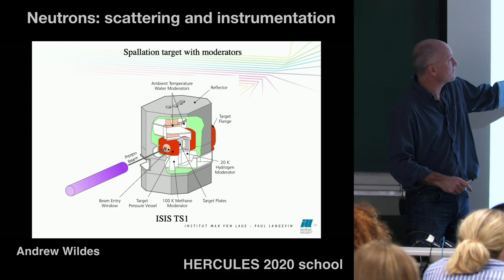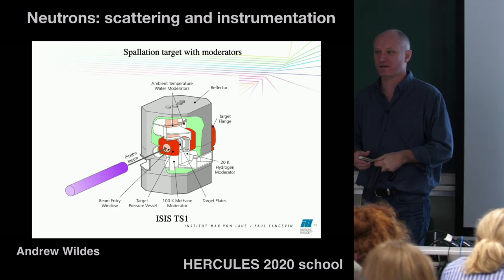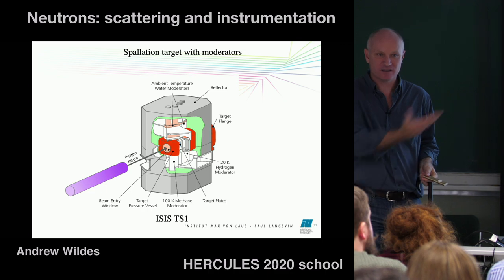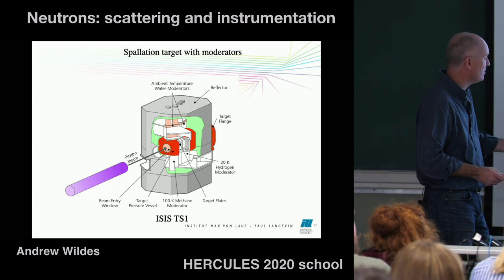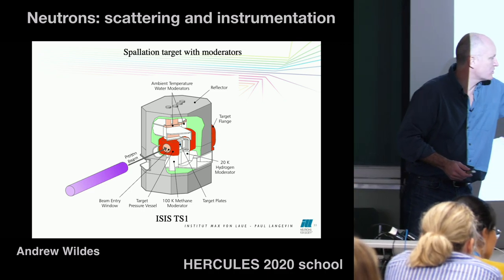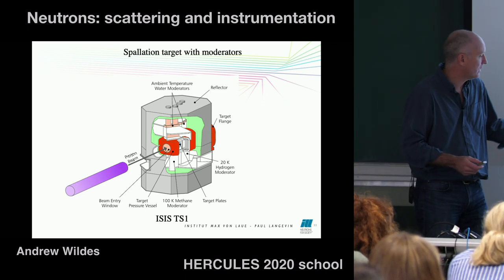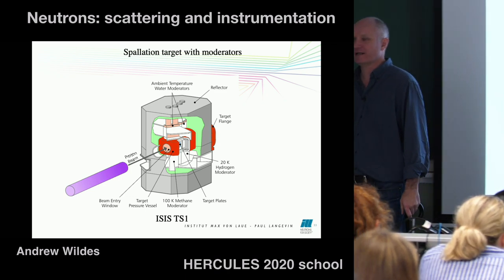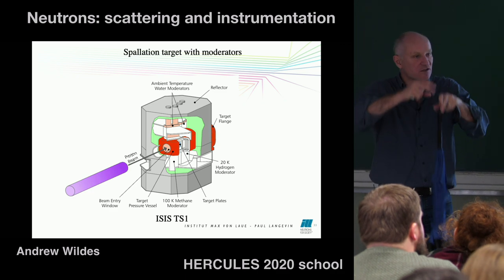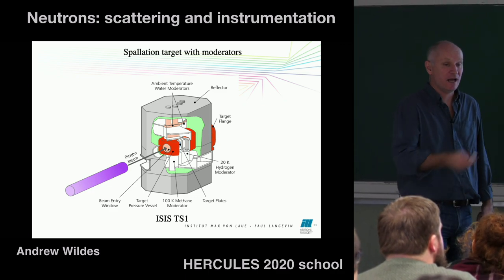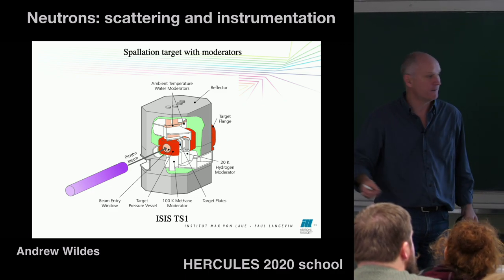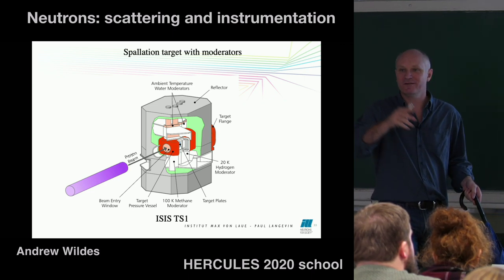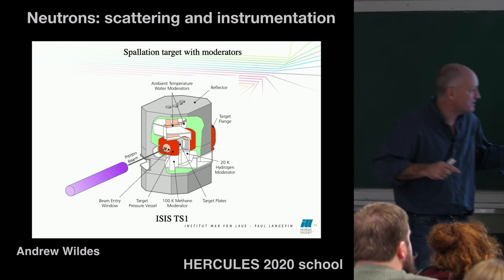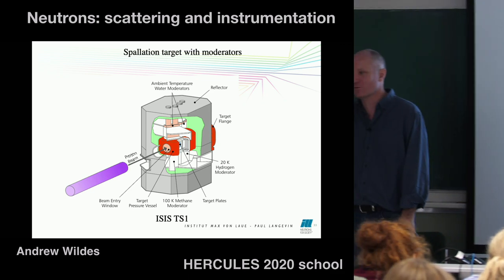So here above the source, you've got ambient temperature water. So this is like a thermal moderator for a spallation source. And underneath, you've got a couple here. There's a hydrogen moderator at 20 Kelvin, and there's another one here, methane at 100 Kelvin. So these are designed to slow the neutrons down to energies that are usable for the instruments. And then you put the instrument that wants those energies pointed to those moderators. And that's an efficient way of being able to use that.